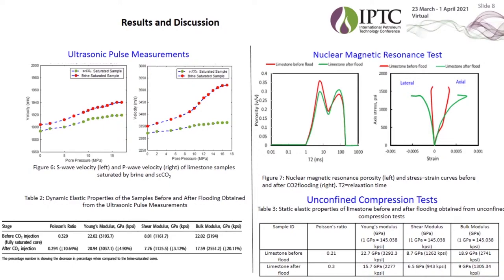Results obtained from the NMR analysis indicate that porosity of the limestone sample has decreased 3-4%, whereas the T2 time range was shifted to the right, perhaps because of the creation of small pores. This slight decrease in the porosity could be linked to the dissolution of calcite, which was transported from the injection sites and blocked the pore space downstream.